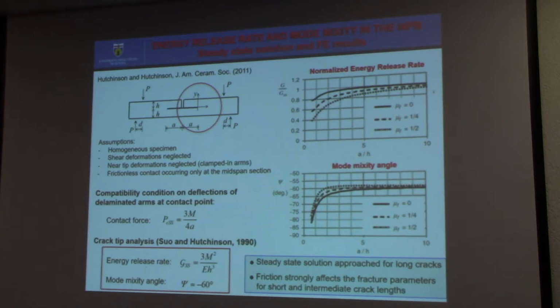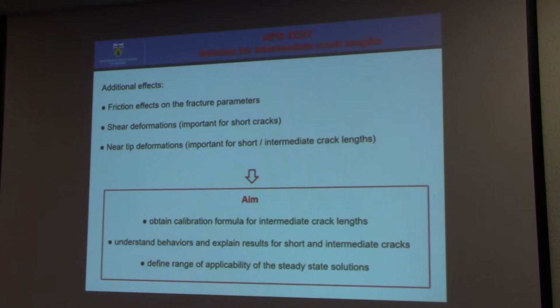And what you can see from this diagram is that it's true that the steady-state limiting solutions are approached, but these occur only for very long cracks, while the solutions for short and intermediate cracks strongly depend on the friction acting at the point of contact, and the solutions are also affected, as you can see, they differ from the steady-state solution. So our idea is to formulate a mechanical model for this specimen which accounts for all the effects that were neglected in the original solution.